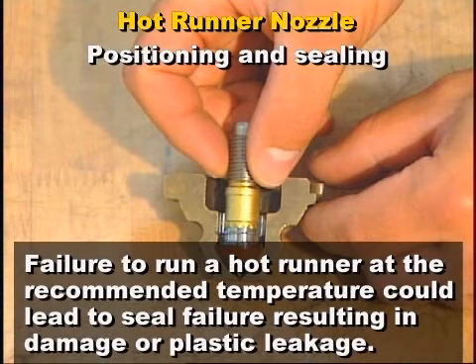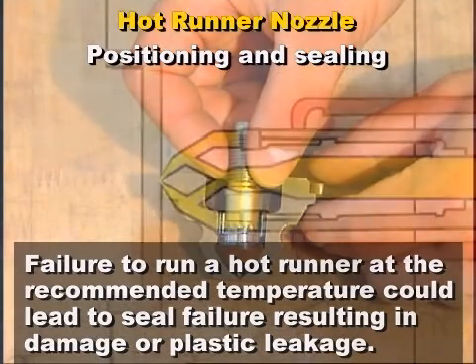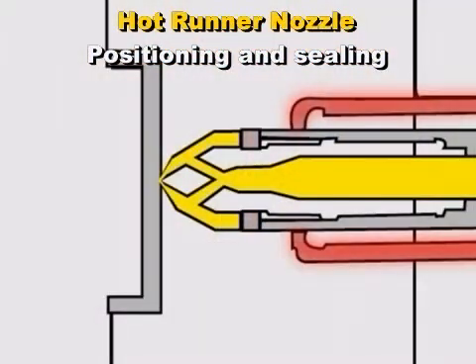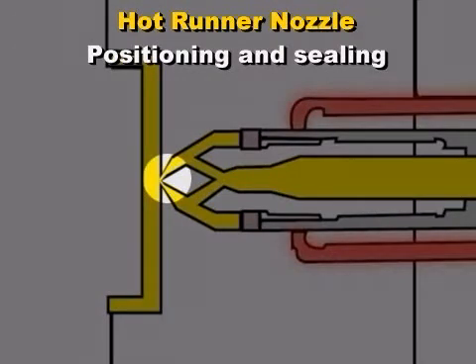Failure to run a hot runner at the recommended mold and nozzle temperature could lead to seal failure, resulting in damage or plastic leakage. The amount of thermal expansion is critical as it generates the force that prevents leakage between the nozzle tip and gate. Too much force may damage or deform the metal here. Too little and plastic leakage may result.